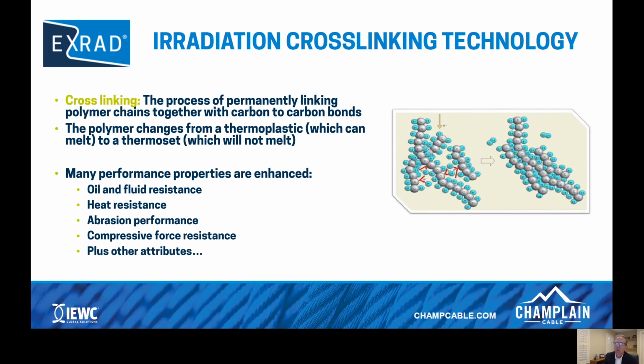So now we'll move into cross-linking technology and specifically irradiation cross-linking technology, which is Champlain's preferred method. But let's define cross-linking first. Cross-linking is the process of permanently linking polymer chains together with carbon-to-carbon bonds. And the polymer then changes from a thermoplastic, which would melt under excessive heat, to a thermoset, which will not melt under excessive heat. And when you do this process and get these carbon-to-carbon bonds, many other performance properties are enhanced, such as oil and fluid resistance, heat resistance, abrasion performance, compressive force resistance, pinch, crush, and so on.